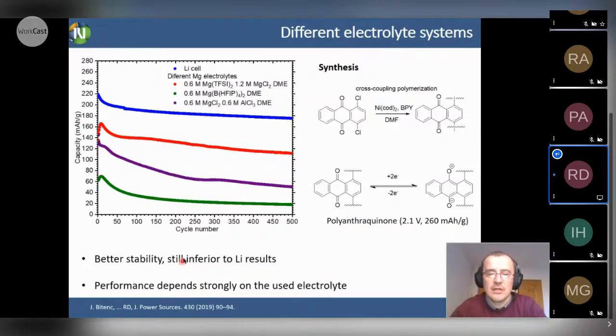So then I would like to share with you also our knowledge about the importance of electrolyte, the importance of the composition of electrolytes. Here's just one example working with an anthraquinone molecule, and this anthraquinone molecule is directly polymerized without a sulfur linker to polyanthraquinone. And in the lithium system, you can see we can obtain very nice capacity retention, relatively good stability with some capacity fading at the beginning. And capacity is around 220 at the beginning out of 260, which is the theoretical capacity.